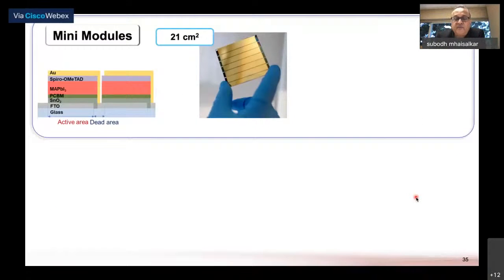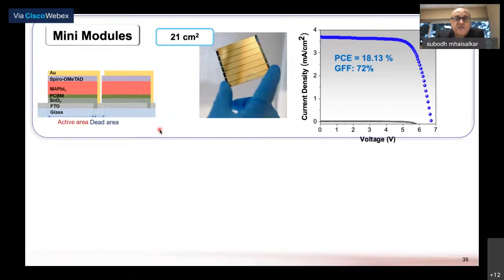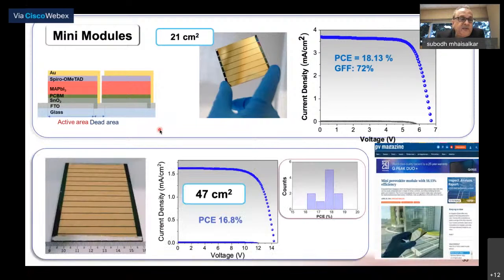What we had not completed, and this is work which is ongoing, is that for making mini modules, you really need to come up with different processes that could take care of the individual scribing of the ITO as well as the active layer. And this scribing, we began doing. The P1 in this case was done with laser, and the P2 and P3 were done manually. We have made mini modules that range from sizes of about 21 to 47 centimeters square. As you can see in this histogram, the distribution is not bad. The largest modules give us in excess of 16 to 17%, with very decent VOCs, JSCs, as well as fill factors.